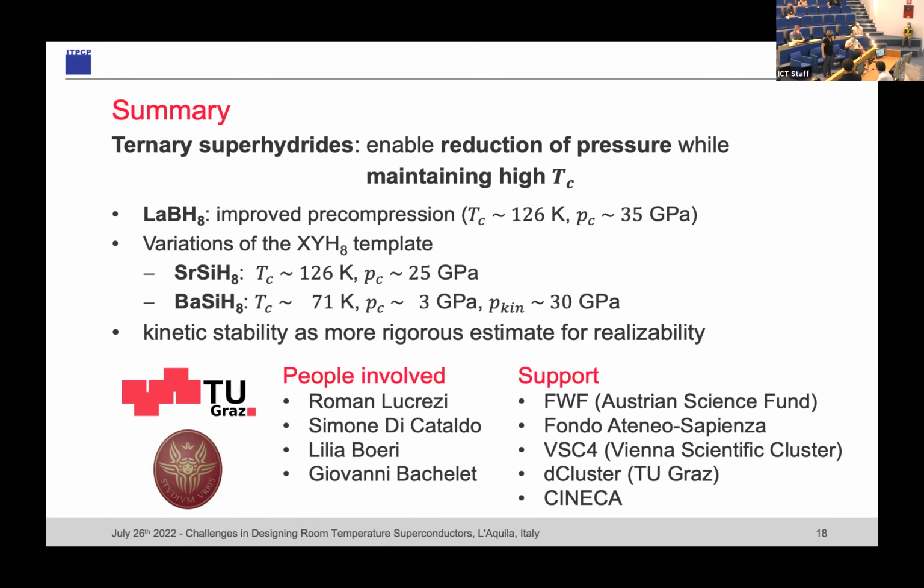Is it clear what, well, not experimentalists, but so much as the chemists, I guess, need to do to reach this kinetic stability region? Like, is it obvious that they can actually synthesize things? Right. I mean, I have my ideas, but I'm a theorist, so they might be completely wrong. So yeah, our ideas would be that you need to synthesize them at the high pressure, but that you're then able to quench it down to the lower pressures because they are protected. They should be protected by this enthalpy barrier.